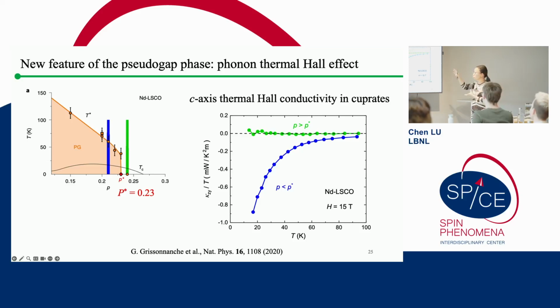One thing about cuprates is that they are highly 2D materials, which means all the electrons or even magnons are highly confined inside the 2D copper oxide plane. So if you want to apply the heat perpendicular to this plane, there is only one type of carrier left that can carry heat for you, which is the so-called phonons. And then we measured this c-axis thermal Hall conductivity, which is a direct measurement of the phonon thermal Hall effect itself.